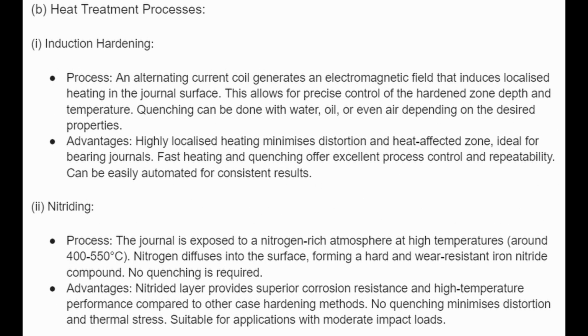B. Heat treatment processes. 1. Induction hardening. The process: an alternating current coil generates an electromagnetic field that induces localized heating in the journal surface. This allows for precise control of the hardened zone depth and temperature. Quenching can be done with water, oil, or even air, depending on the desired properties. Its advantages: it has highly localized heating, minimizes distortion and the heat-affected zone, ideal for bearing journals. Fast heating and quenching offer excellent process control and repeatability. It can be easily automated for consistent results.